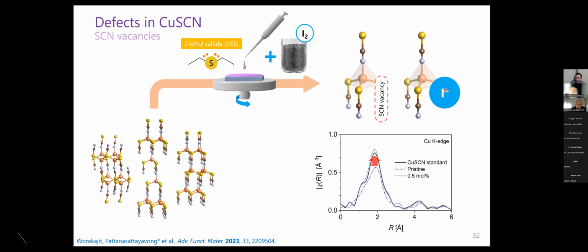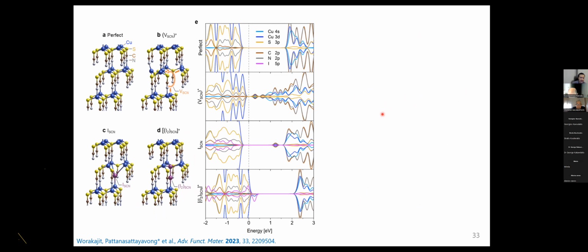So iodine, we actually add as I2, but at the optimal concentration, it becomes I minus and then fills in the SCN vacancy. Note also that iodine has the same valence state as SCN. SCN is also 1 minus. We also did the DFT with our collaborator, Professor Adisa at Kasetsart University in Thailand.